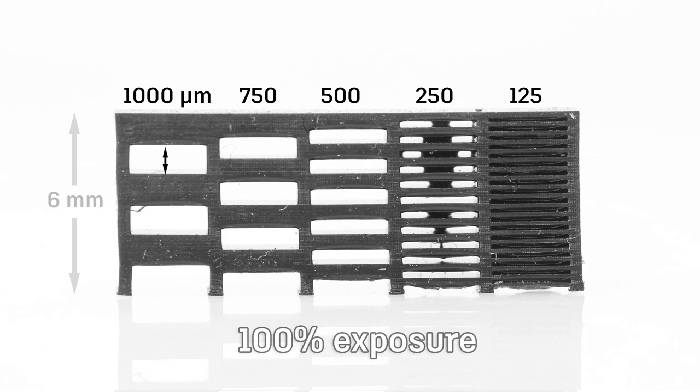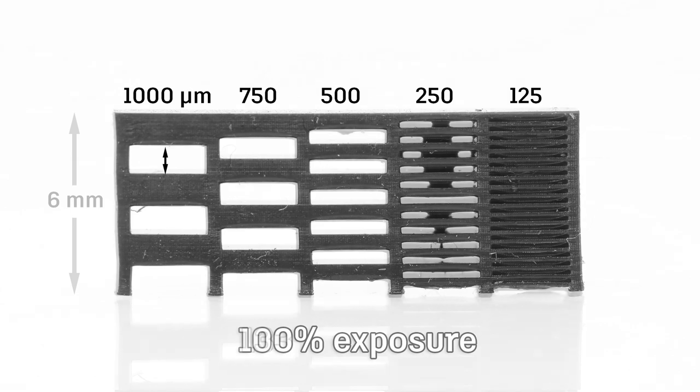but the 125 micron features are completely filled in. If we add just 33% more light exposure, the 250 micron features are completely filled in, and we have effectively lowered our resolution.